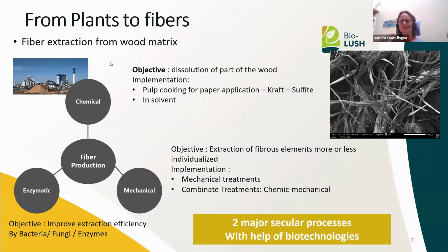If now we consider the production of fibers from wood, production is different from what we can obtain with annual plants. Of course, to obtain fiber from the wood matrix, we can apply mechanical treatment. Mechanical treatment can be performed with a refiner, with or without steam addition, with the objective to extract fibrous elements more or less individualized. Depending on the type of application, for insulation, for example, it is not a problem to have some chips with aggregates of different fibers together. For pulp use, individual fibers are more necessary. To obtain higher degradation and individualization of the fibers, this mechanical treatment can be combined with chemical or enzymatic treatment.